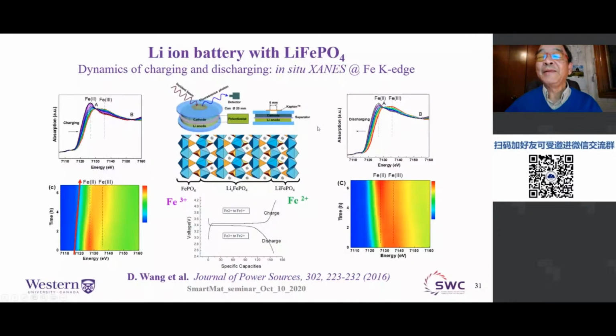Now, this kind of experiment is unique for every type of material. In this particular experiment, you use submicron lithium iron phosphate nanoparticles. If you change the size of the particle, the behavior changes too. This is sometimes why everybody doing the same experiment has different results, because their microstructure is different.